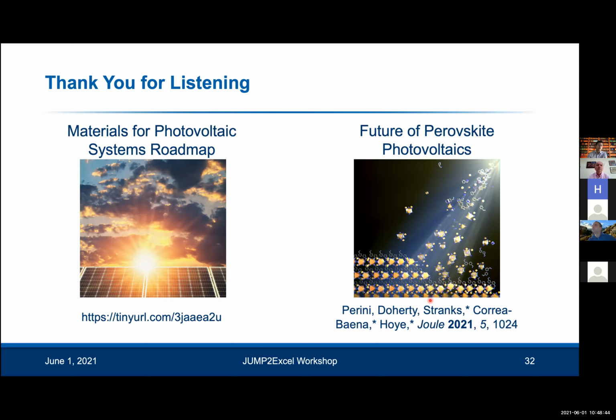So for example, for perovskite-silicon tandems, for the perovskite top cell, you need to have a transparent conducting oxide. And what people have found to be quite effective as an anti-reflection coating there is lithium fluoride or magnesium fluoride. And people are doing optical simulations to work out the optimum thickness for these materials. I don't do this myself, but there are other groups working on developing new anti-reflection coating materials. Okay, thank you, sir.